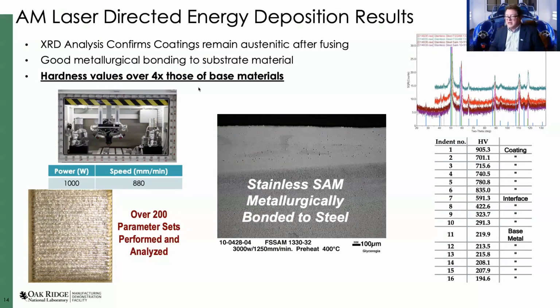And this is an example where we use laser deposition to fuse these coatings down. We showed that our hardness values increased over the base material. These are hard steels as we begin with, on a Vickers, about 200. We can get about a 4x increase in the material properties as we use this.